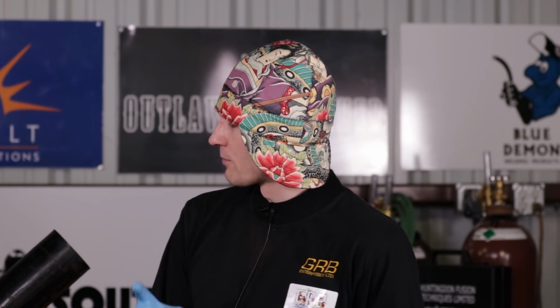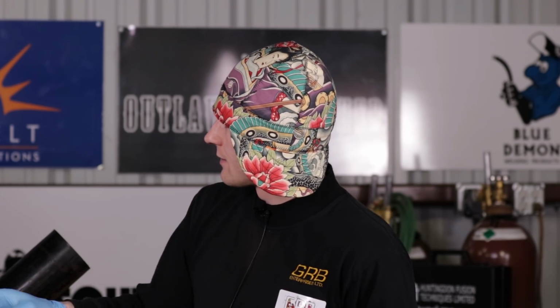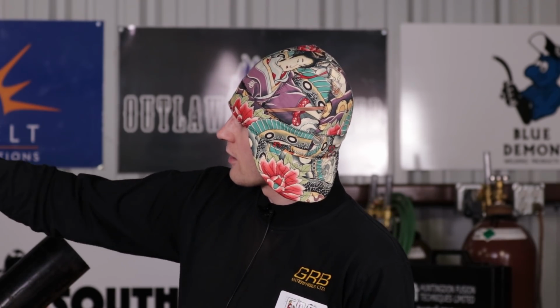I was very particular, and he wanted this material gummed together because this particular application was not going to be X-rayed. It was just going to have plastic pellets flowing through it. But the problem with that, and I explained it to him, but it kind of went over his head, is that the oxide melts at 3700 degrees Fahrenheit. The material underneath the oxide melts at 1220, and because my weld puddle does not remove the oxides, I cannot just gum it together. I cannot weld over the oxides.